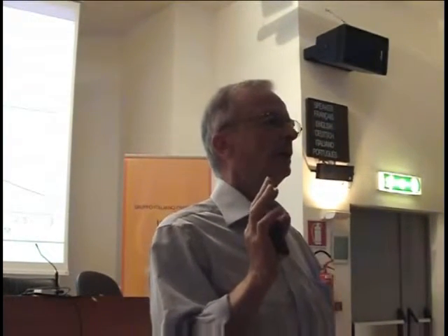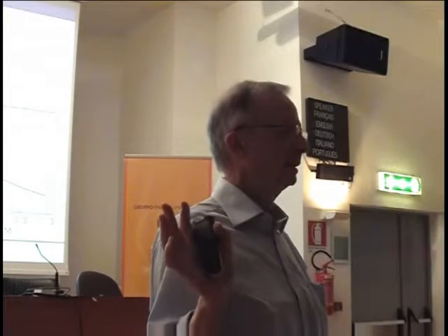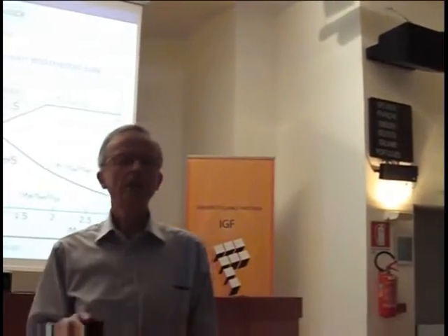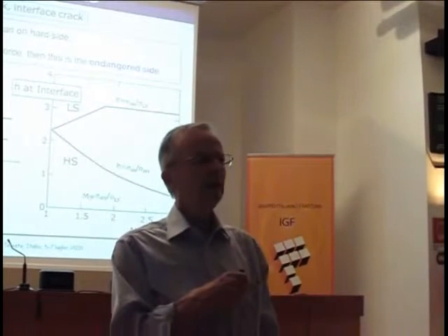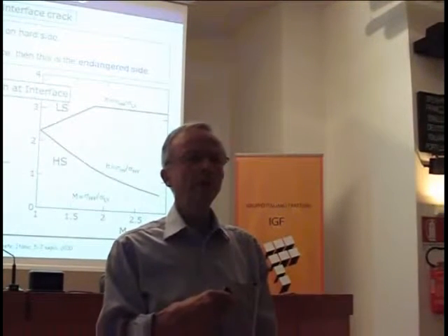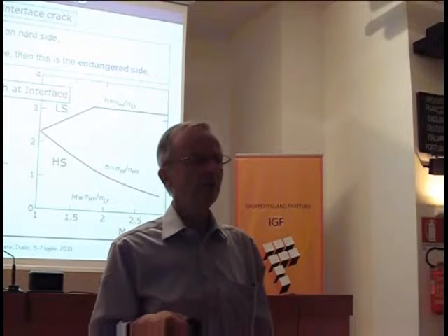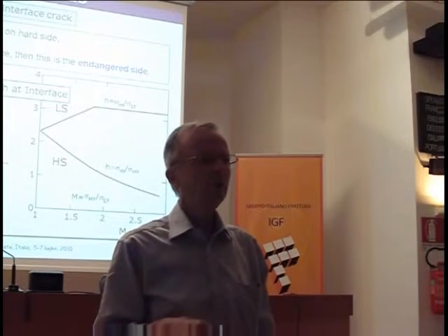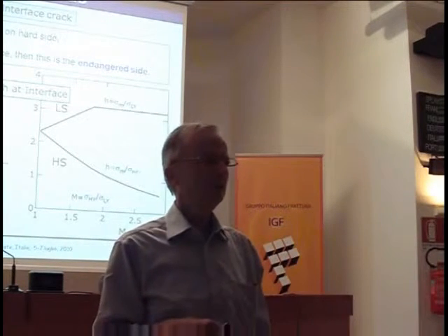I mean, it would work in terms of the driving force delta G, but what about the right-hand side? The material's resistance. When we measure fracture toughness, we have standard specimens, plane stress or plane strain, thick or thin, whatever. And now here we have variable constraints for which we have no test methods. So I have to think about how to characterize the material.